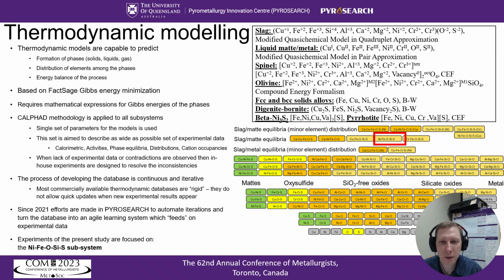We use modified quasi-chemical model for slag with two sublattices and quadruplet approximation. For liquid matte metal, we use the modified quasi-chemical model with one sublattice in pair approximation. And for complex solid solutions such as spinel and olivine, we use the compound energy formalism. But the accurate predictions with these models still depend on experimental data used to establish model parameters.